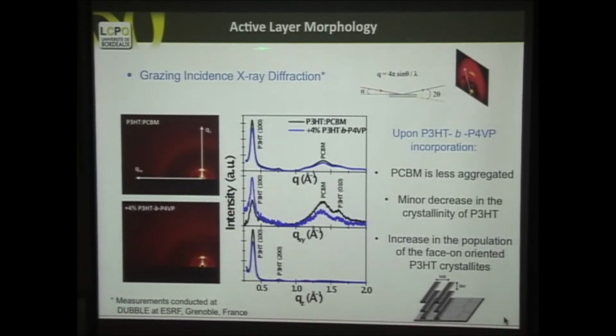So we did what we call grazing incidence X-ray diffraction. We have the X-rays coming out, and we see the spectrum, and we try to analyze the structure of this thin film. So you see here the total, when we take the radial integration of all the intensity around, we see that before annealing, as cast, we have high crystallinity of P3HT, and then it reduces a little bit when we add the block copolymer, and also the aggregation of the PCBM. This is the fingerprint of the PCBM. It reduces a bit when we add the polymer. So the crystallinity reduces a bit, but that's not a great problem, it's actually good.